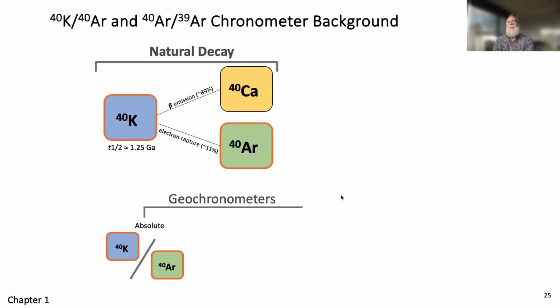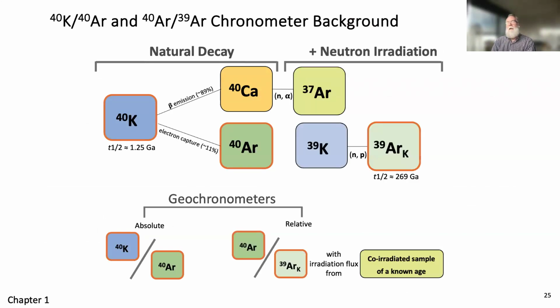So Argon-Argon dating, I don't know how familiar you are with it. It's a form of potassium-argon dating, where potassium-40 decays to calcium-40 and argon-40. And in potassium-argon, you measure both the potassium-40 and the argon-40 to get an age. But it's easier if you do this. You irradiate this sample with neutrons. That'll transform the calcium-40 to argon-37, and it transforms potassium-39 into argon-39. And then you measure the ratio of argon-40 to argon-39.